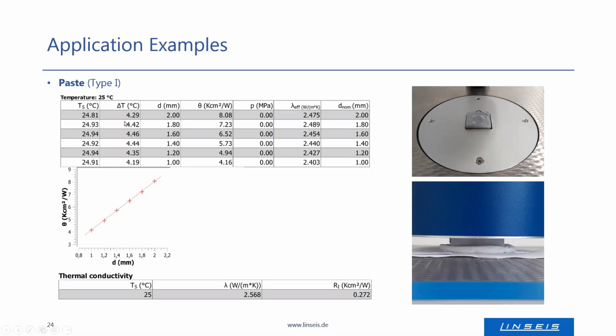The measurement was performed at room temperature with a temperature gradient of about 4 to 5 degrees Celsius. This means the upper meter bar was about 2.5 Kelvin hotter compared to the sample temperature, and this also counts for the lower meter bar. The thickness was reduced from 2 to 1 millimeter.